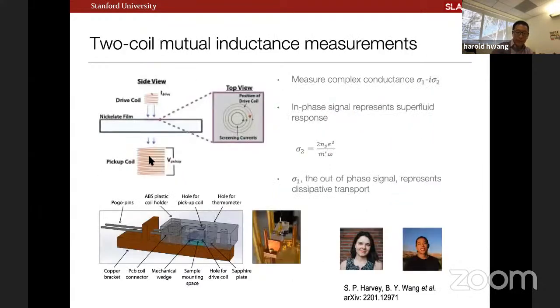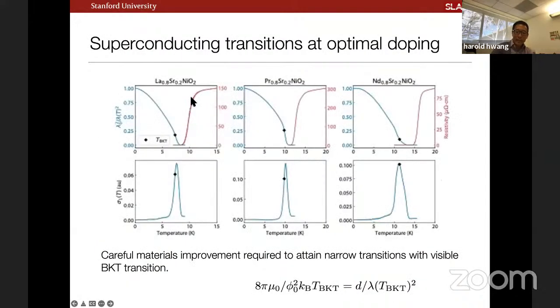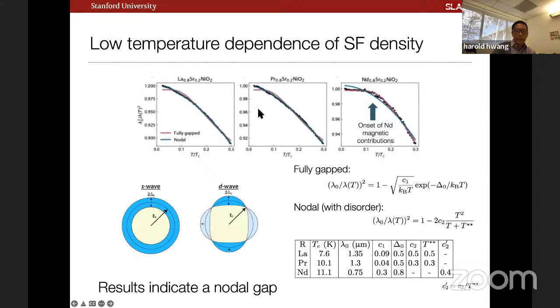Maybe one thing that I forgot to mention is the scale of our coil is on the scale of 0.4, 0.5 millimeters. We're still constrained to relatively small area thin film samples. And so, the challenges of having homogeneity on a larger length scale and so forth is really what underlies this kind of work. And just in maybe one last slide, let me show you what we can say right now about the low temperature regime of the superfluid density.